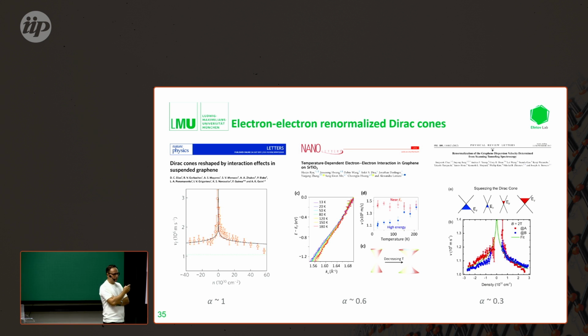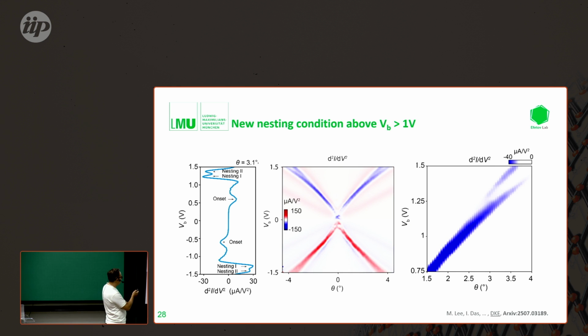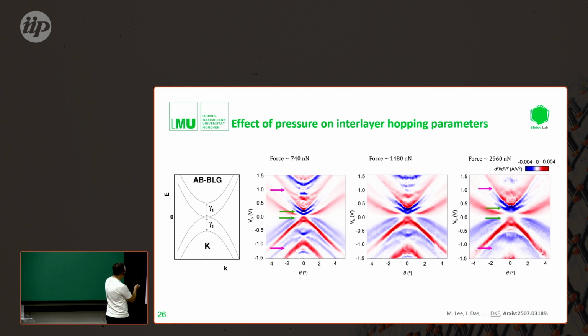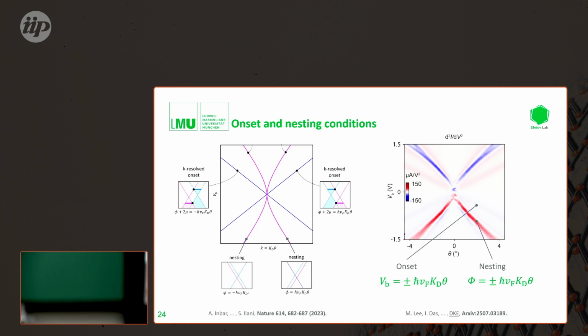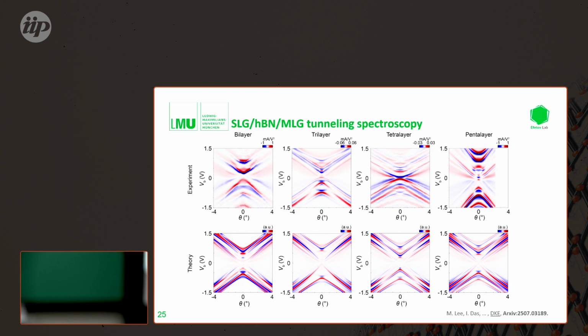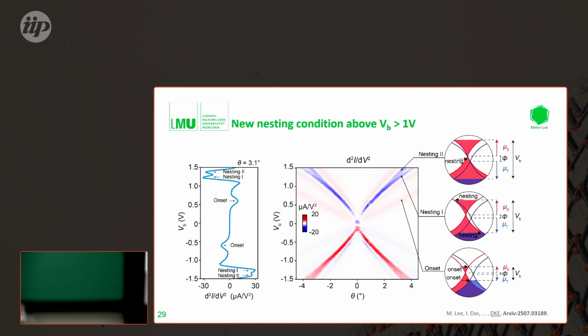It appears at larger k, yeah. So you have to think about how the bands overlap. This is the cartoon picture for linear dispersion, and this is the cartoon picture for what happens with this type of correction. You will see that the two kissing points that you get for the slight nonlinearity run very closely to one another at low bias, and only at high voltages can you see the splitting.